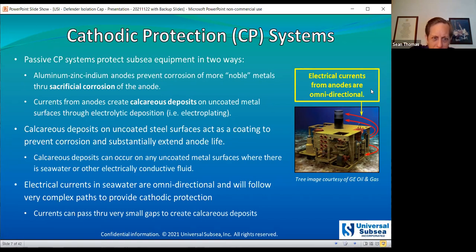These can occur on any metal surfaces that are uncoated, where you have seawater and you're electrically coupled to the anodes. Now, the currents coming from the anodes are omnidirectional. They'll follow very complex paths, so it doesn't have to be a line of sight. It'll follow zigzags even. The currents will also pass through very small gaps. As long as you have an electrically conductive fluid in the gap or downstream of the gap, currents will pass through those gaps, and you can see calcareous deposits downstream of the gap.